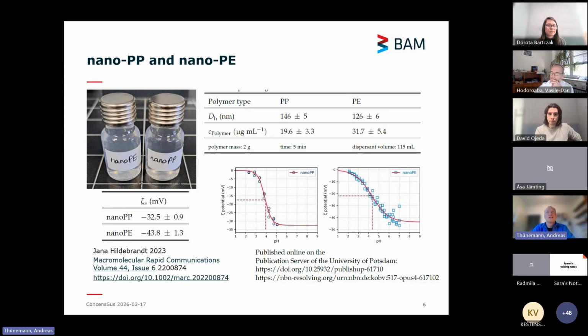The diameter of the particles does not depend much on the type of polymer. Polypropylene is a little bit different from polyethylene, something around 146 and 126 nanometers. The polymer concentration is typically in the range of 20 to 40 micrograms per milliliter, so this is relatively low. I said the particles are stable for a long time in this aqueous solution. I want to mention that before filling the particles into vials, we heated them up to 80 degrees C for 3 hours, just to make sure that not many microorganisms are still in the bottles, because we have only water and polymers, and microorganisms may grow in these vials.